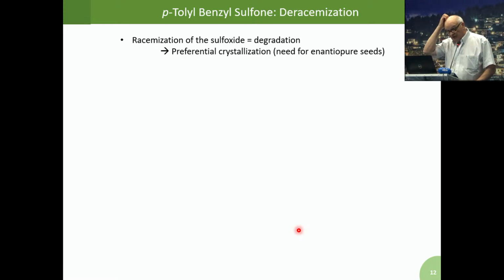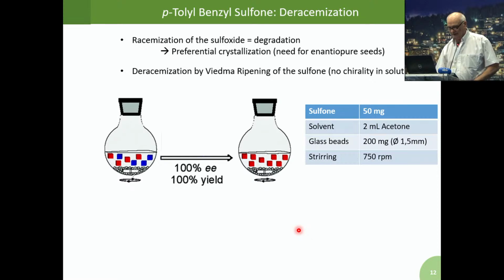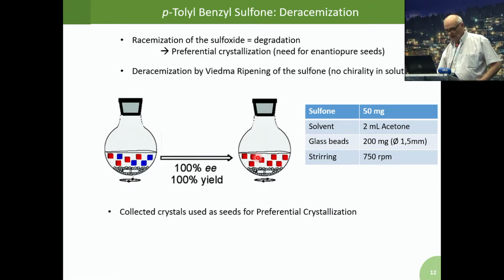Okay, so as there is no deracemization with the sulfoxide, we said, okay, but with the sulfone, we will be able to deracemize, because here there is, of course, no intrinsic chirality, so we have only the two possibilities of crystal packing. And then we implemented the Viedma ripening on the sulfone, as it was difficult to monitor because it's only chirality in the solid state, and at that time I didn't have a VCD in my lab. So we decided to do it for 1 week. We use glass beads that you can see here and the magnetic bar. So we were constantly grinding the crystals, and then you have this irreversible evolution towards one of the two enantiomers. And then we collected these crystals as seeds for the preferential crystallization, okay? And we repeated this experiment several times to have a collection of different possible enantiomers, okay?